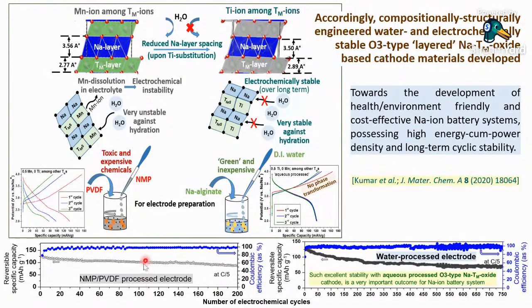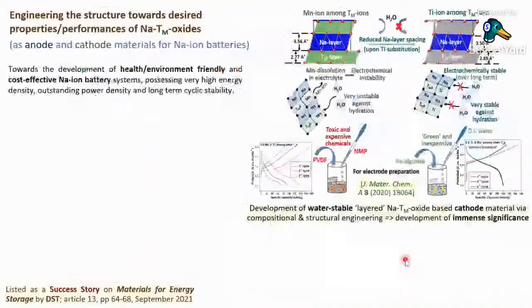So one can see the comparison between NMP processed and water processed electrode. This is up to 200 cycles, this is up to 750 cycles, and one can see hardly much difference in terms of the cyclic stability between the NMP processed and the aqueous processed cathode material.